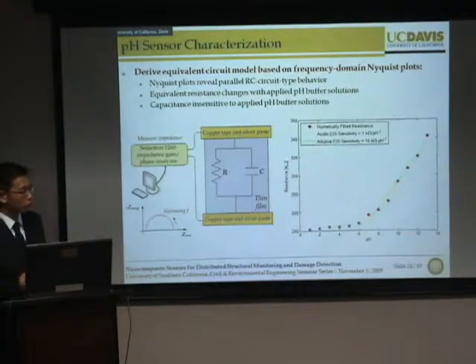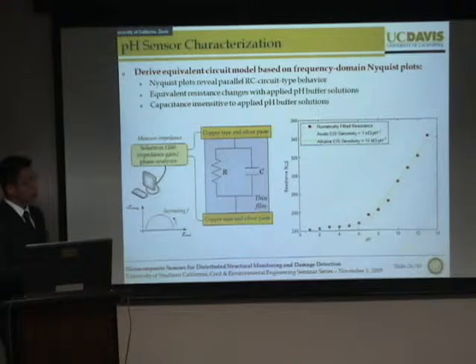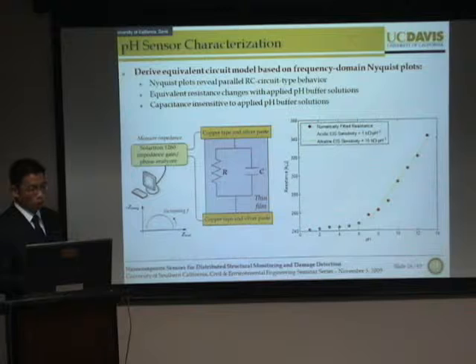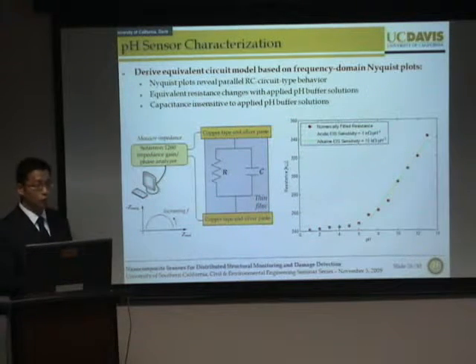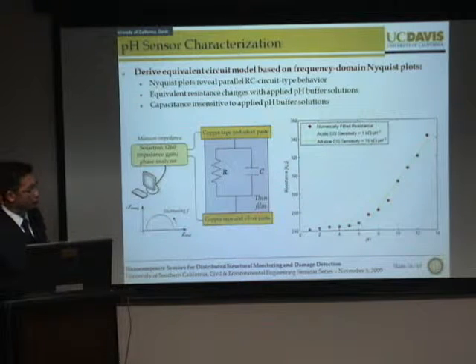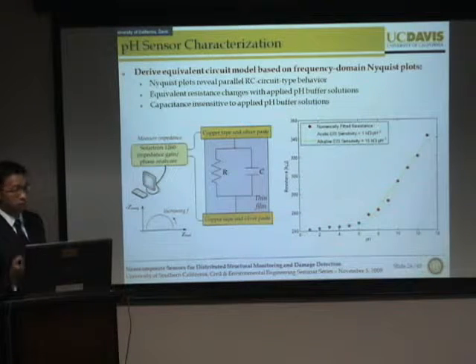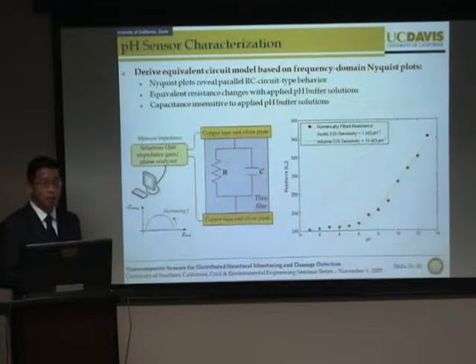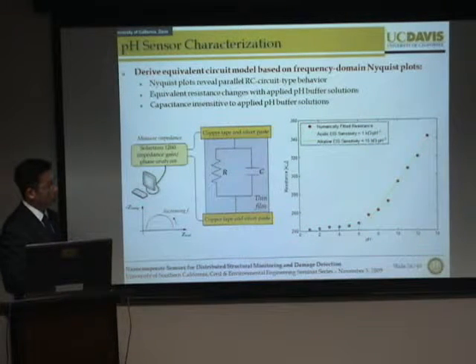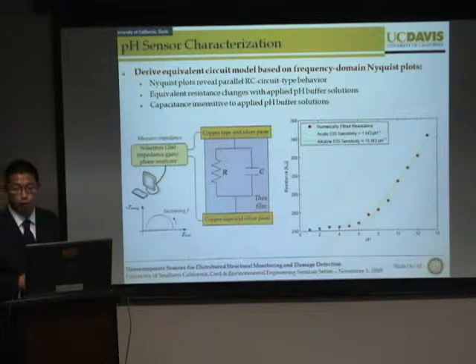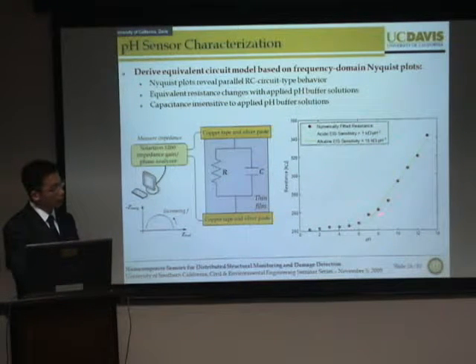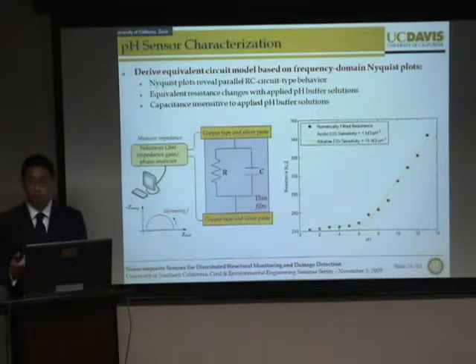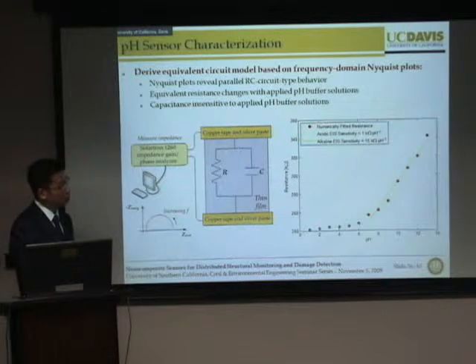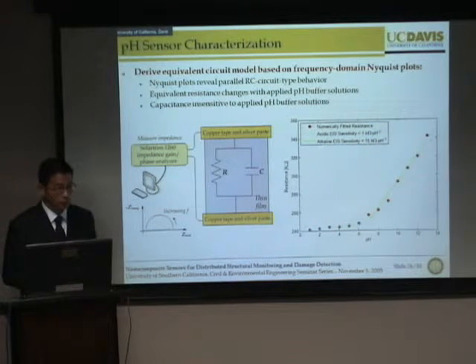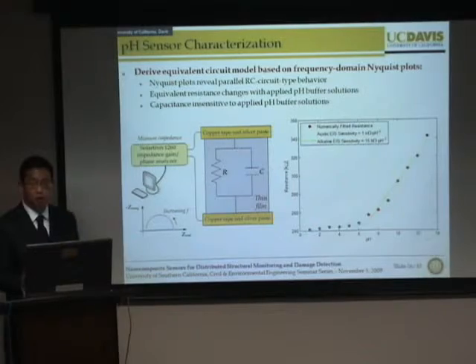So to investigate what this material behaves like, we then fitted the experimental data to a simple RC parallel circuit, where we can then back out the calculations and look at how the resistance and capacitance changes as a function of applied pH. So upon model fitting, using a simulated annealing algorithm, we see that the pH thin film does in fact behave bilinearly, where in the acidic region, the material has a pH sensitivity of approximately 1 kiloohm per pH. But in the alkaline domain, where it's important for reinforced concrete corrosion studies, the sensitivity is much higher, approximately 15 kiloohms per pH, which suggests that there is some promise for using this type of material for detecting pH changes.